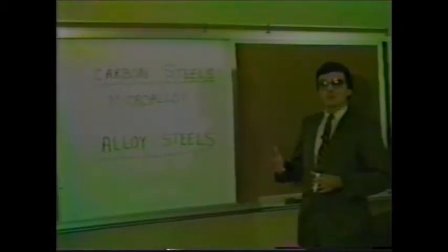Now, if you have a microalloy steel that has the same yield strength as a cold-drawn bar, it turns out that the tensile strength of the microalloy is more than a cold-drawn bar, and therefore its machinability is not quite as good as a cold-finished bar. Also, if you have a microalloyed bar that has the same tensile strength as a cold-drawn bar, it will have a lower yield strength. Another aspect of microalloyed bars is that they can be cold-drawn. And when you cold-draw a microalloyed bar, you can achieve strength levels that could not be gotten with cold-finished bars of the same grade alone. Now, all of the strengths and elements that we're talking about are contingent upon the bars having a good internal structural integrity.